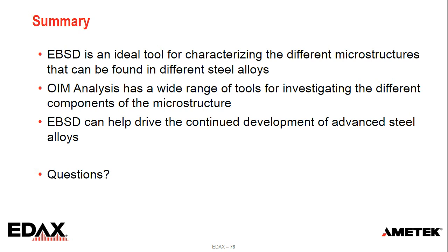There's a couple of questions here that are essentially about spatial resolution, one in terms of retained austenite and one in terms of carbide in the nanometer range. The nanometer range starts to get small for regular EBSD. The spatial resolution is probably somewhere between 20 to 50 nanometers as a ballpark. And it's very difficult to describe, because it will change depending on the atomic number of what you're looking at.